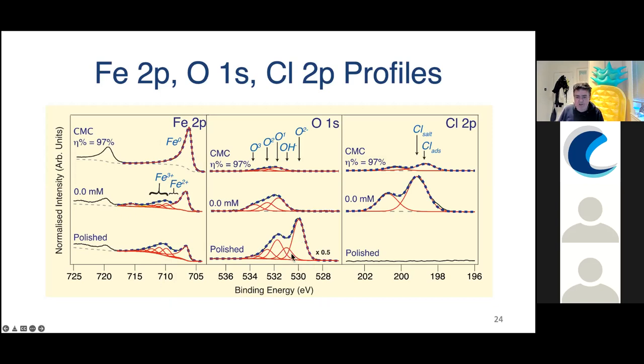If we look at the oxygen signal now, that's consistent with it, because the oxygen signal has oxide and OH, and they're removed as soon as you put it into the acid with or without the inhibitor. O1, O2 and O3 are due to adventitious carbon and oxygen-containing molecules that adsorb from the atmosphere, even in the nitrogen glove box. They're not related to the system. You just can't avoid those under these conditions.